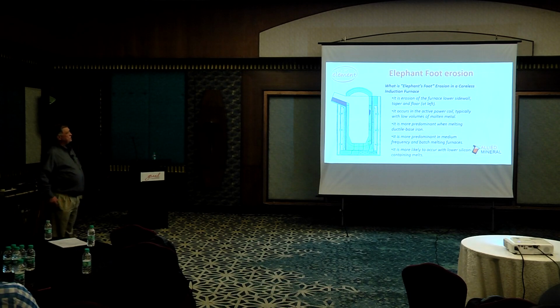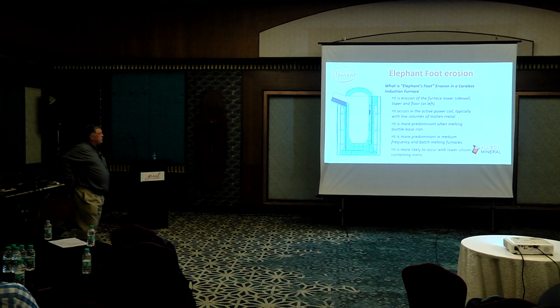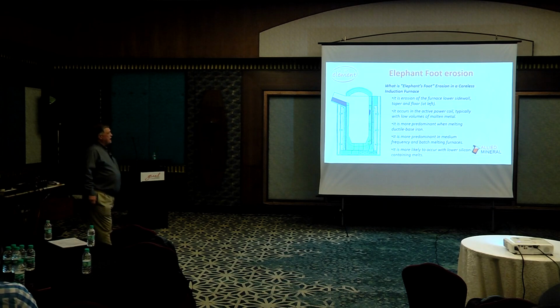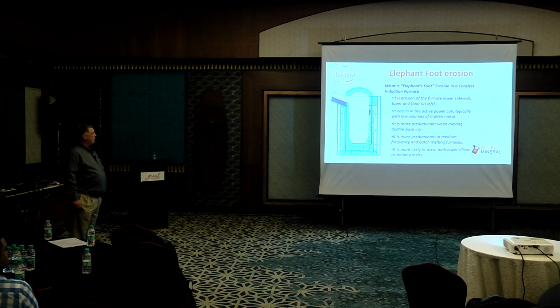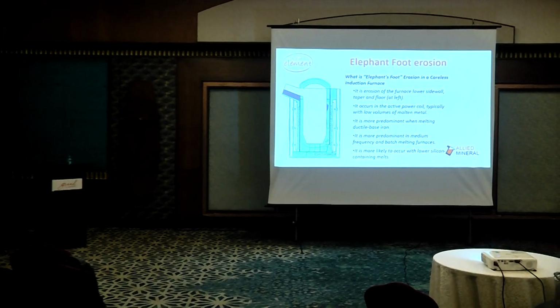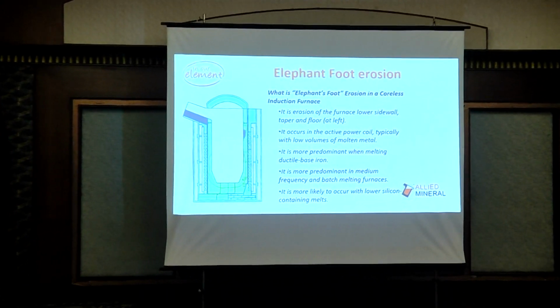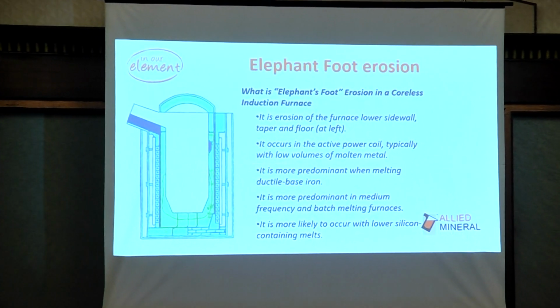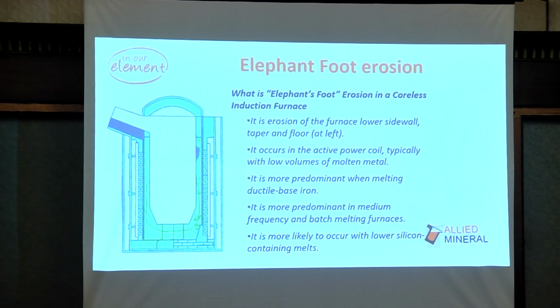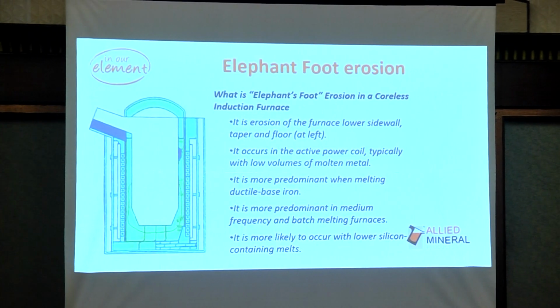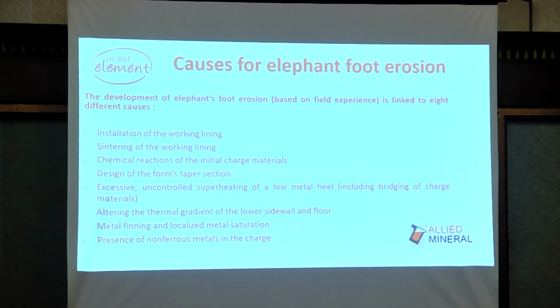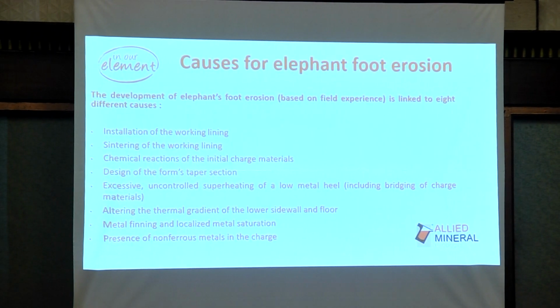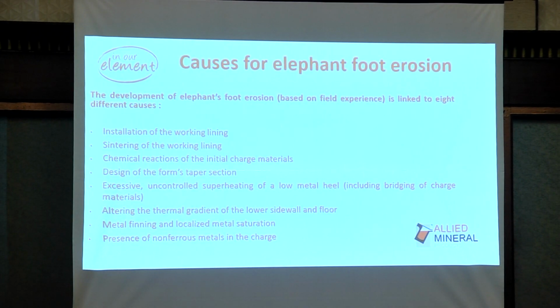So what is elephant foot erosion? It's erosion of a coreless furnace. It's erosion of the sidewall and the taper and the floor. It occurs in the active coil, typically the lower portions of the furnace. It's more predominant when melting ductile iron, and there are several reasons for that we'll go over. It's more likely to occur with lower silicon containing metals. So the development of elephant foot erosion is based on field experiences linked to 8 different causes.